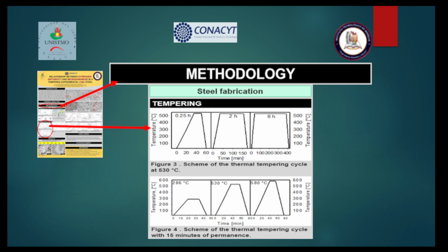At a tempering temperature of 530 Celsius, two more tempering times were tested, 120 and 360 minutes. The purpose of the selection of this temperature and time was to promote the formation of alloy carbide.